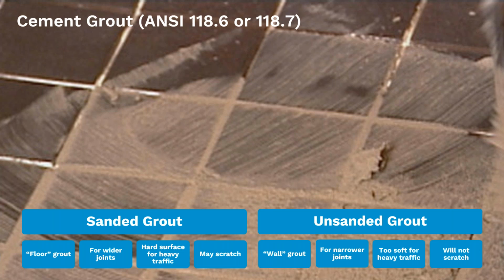With the sanded version, you're really looking at it for that floor grout. And usually you're looking at a 1/8 to a 1/2 inch joint that needs to be filled. It fills in those gaps as you lay down the tile, and it cures to a durable, hard surface that is ideal for heavy traffic, especially with foot traffic and loading. It can expand and contract, but it does contract less than an unsanded grout. Sanded grout can scratch soft stones and glass tiles.